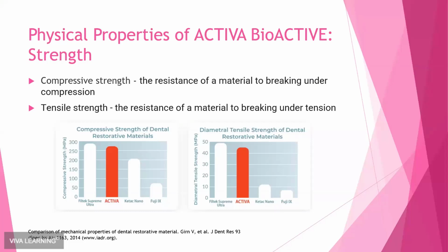So what we're seeing is that the Activa, although it is a glass ionomer derivative, it's really behaving more like a traditional composite. It's comparable to that Filtek Supreme Ultra, and it's outperforming the other glass ionomer materials it was tested against. So then the graph on the right, the tensile strength, which is the resistance of a material to breaking under tension, again, you can see that the Activa is performing more like a regular composite as far as the ability of it to withstand those stresses.